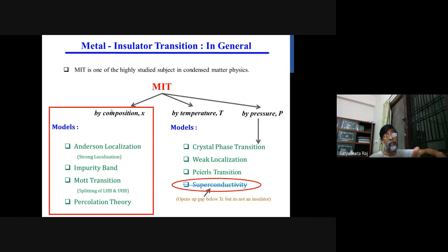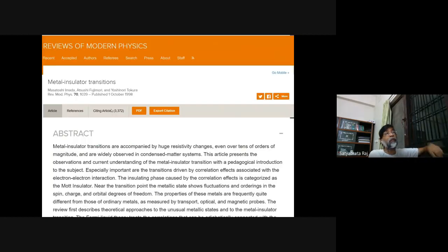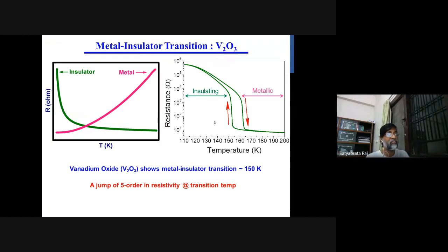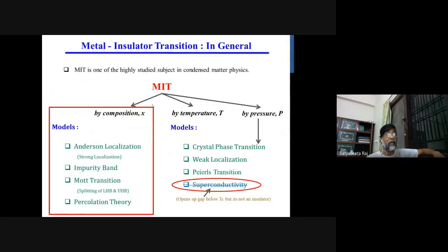The crystal can have a phase transition, whereas in VO2 you can have two different crystal phases. The crystal structure here is something different, and here it is different. So you can achieve an MIT by a crystal phase transition, and weak localization can also explain a metal-insulator transition. There is another transition called the Peierls transition, or the charge density wave transition, which can also make a metal into an insulator. Mostly in this metal-insulator transition, it develops a gap at the Fermi energy. Even in a crystal phase transition, you have a hard band gap.